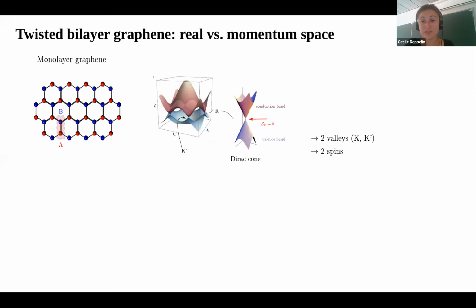Okay, so twisted bilayer graphene. By now you've probably heard this many times, but let me go through it one more time quickly. In monolayer graphene, you have a hexagonal lattice with A and B sublattices. If you diagonalize the Hamiltonian, you obtain this structure where you have Dirac cones at every corner of the Brillouin zone. You have two inequivalent corners, which are called valleys, K and K prime. You also have two spins, so that will give you a four-fold degeneracy.